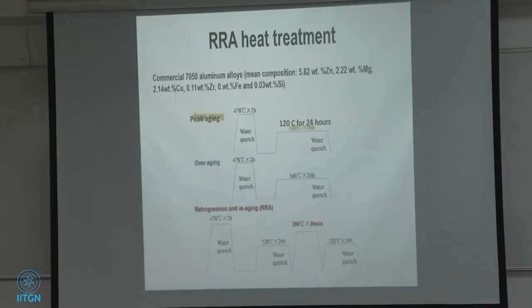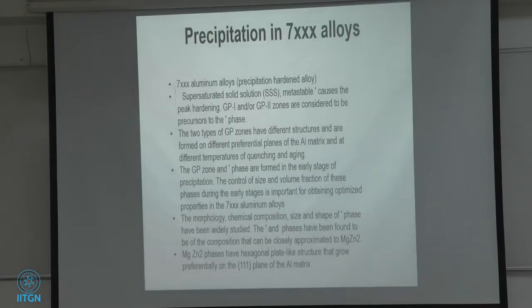There is this zirconium, which is a grain refining agent. It's a grain refiner. It controls the grain size in aluminum alloys. Silicon and iron are junk, inclusions. Okay? So that's the game. That's it. You know everything about aluminum alloys if you know that. Okay. So when you have the supersaturated solid solution, all those elements that I've shown you are in the solid solution. All of them, not iron, not silicon, but magnesium, copper. Those are all in solid solution. And then when you put a little temperature to it, the first thing is eta prime. That should be eta. Eta prime causes the peak hardening.